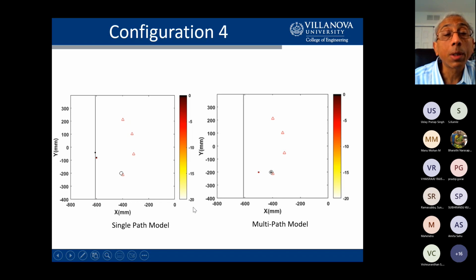But on the other hand, if I exploit the fact that there's multiple pathways for a wave to propagate from a transmitter, arrive at the defect, bounce off the wall, and then come to another receiver, if I exploit all those different paths, then that's called a multi-path approach. And now I can precisely identify where the defect is. Now, the challenge over here was that the defect is very close to the location of one of the transducers. And also there's the edge of the plate very close by. And so multi-path allows us to identify where the defect is pretty well.